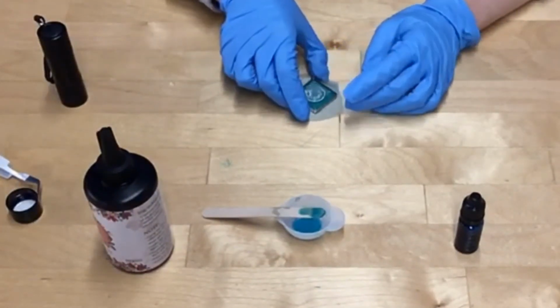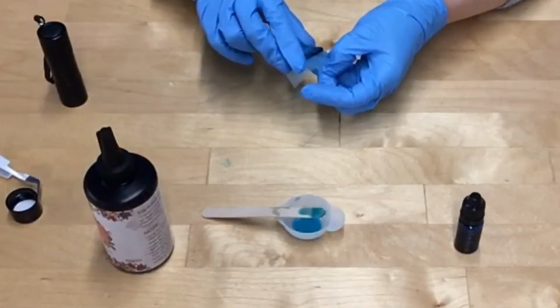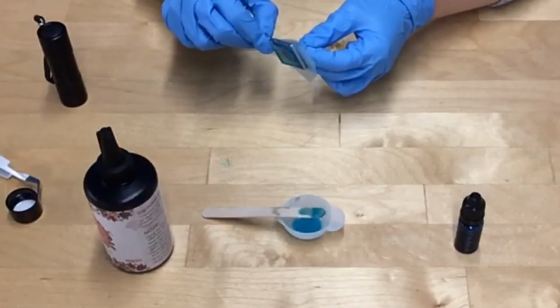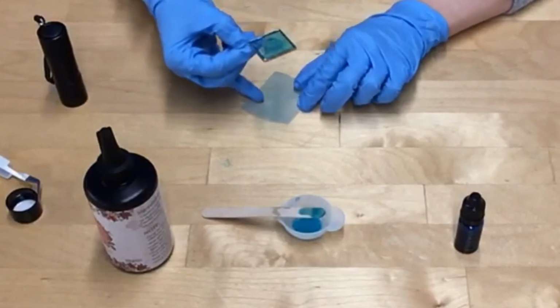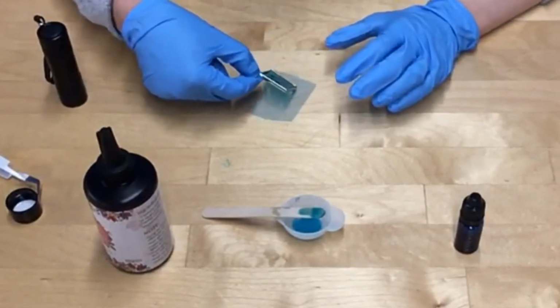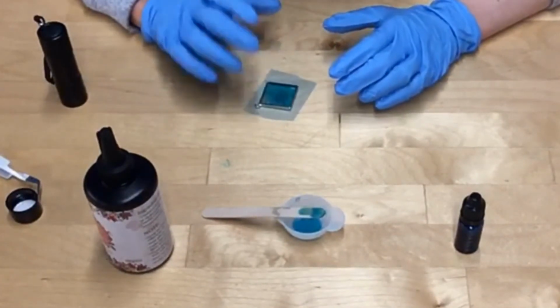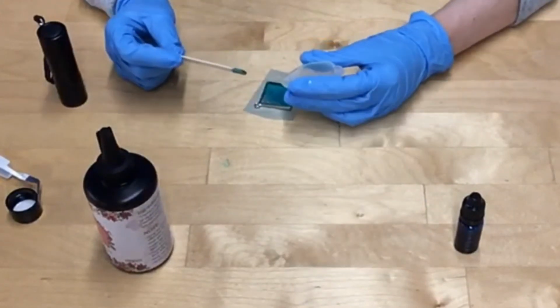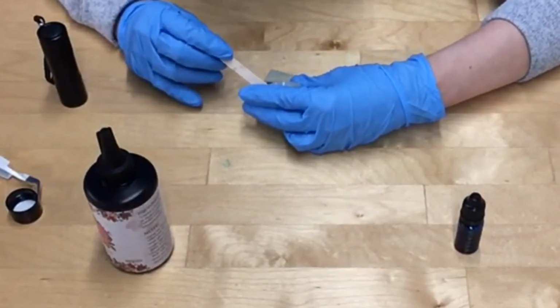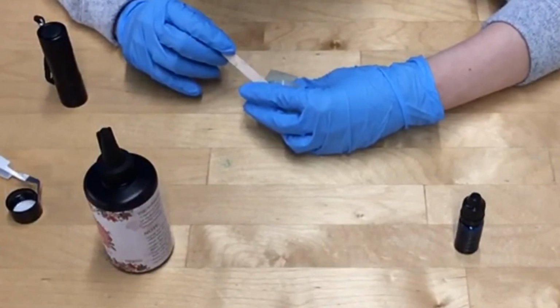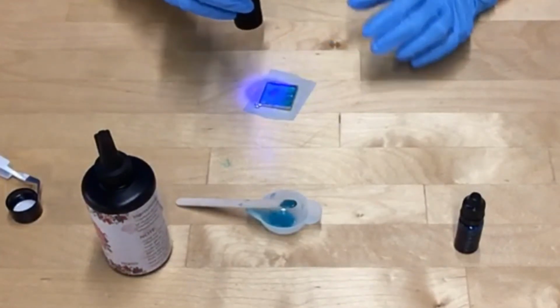After it's cured, you can peel the tape off. Unfortunately, in my case, I ended up with an air bubble on the back side. So I'm going to try fixing that by filling it in with a little bit of resin and curing the back side one more time.